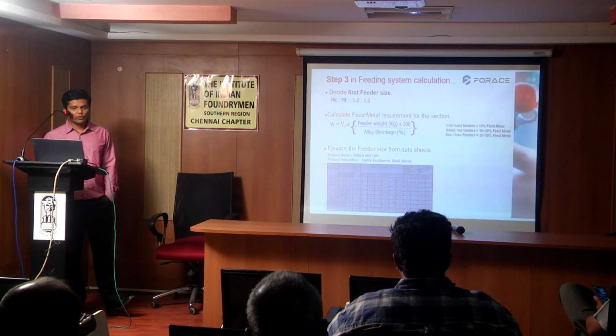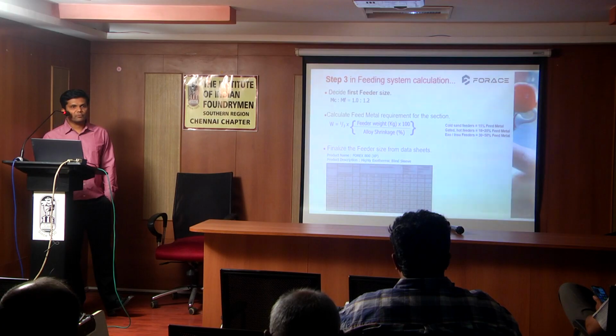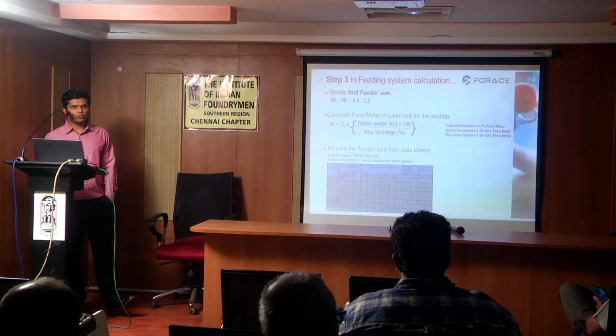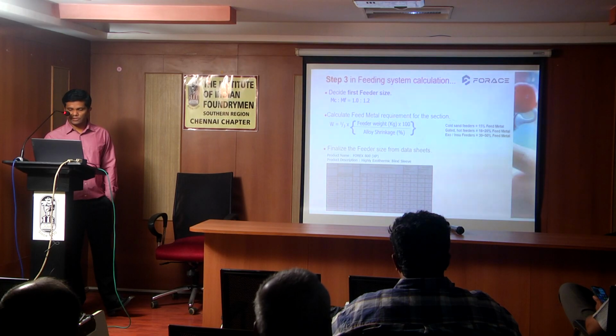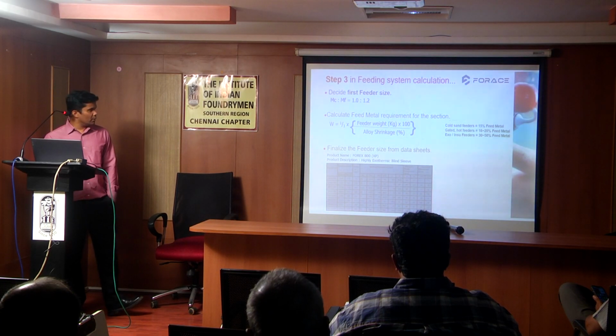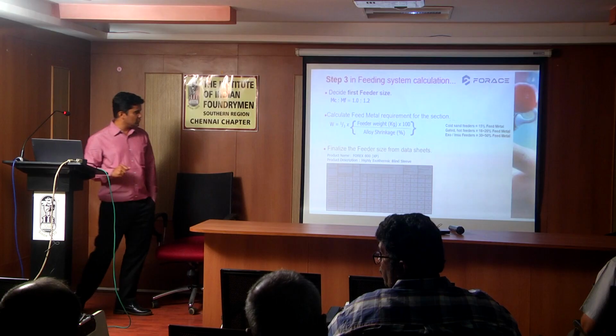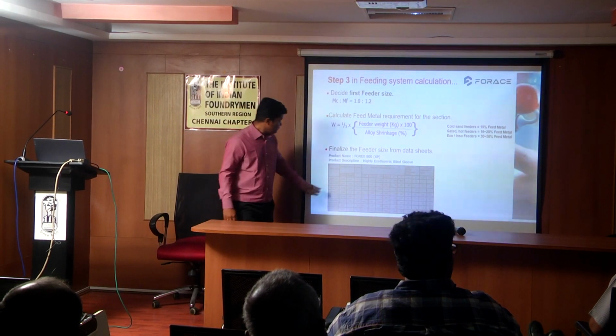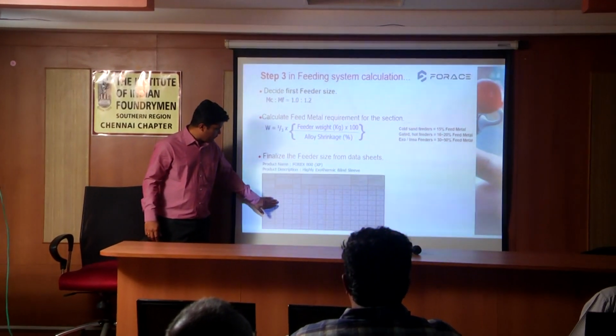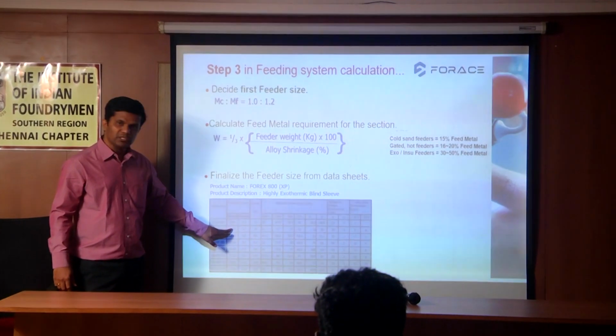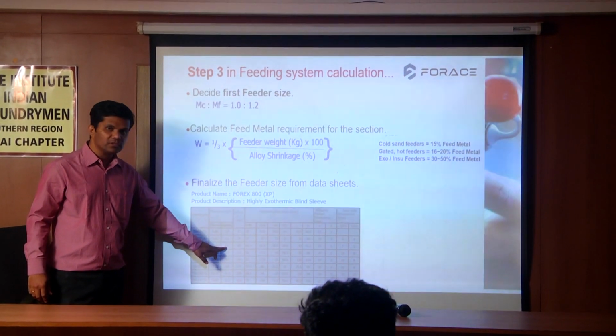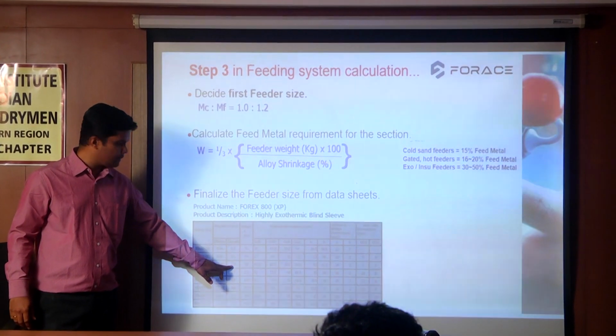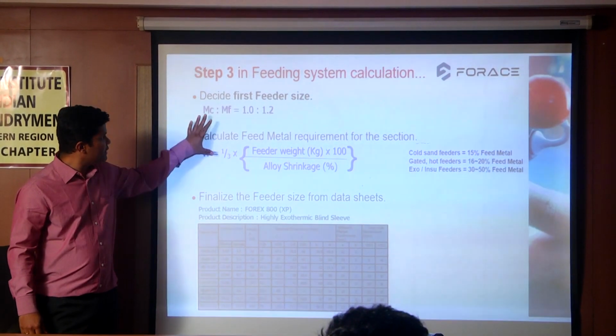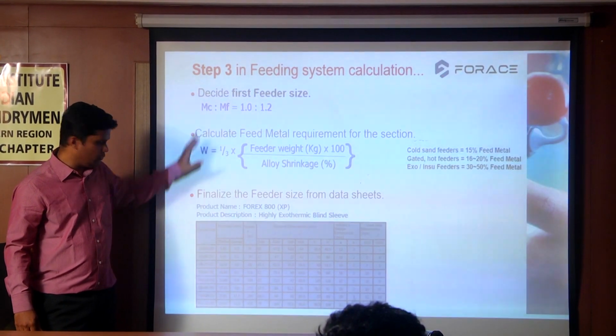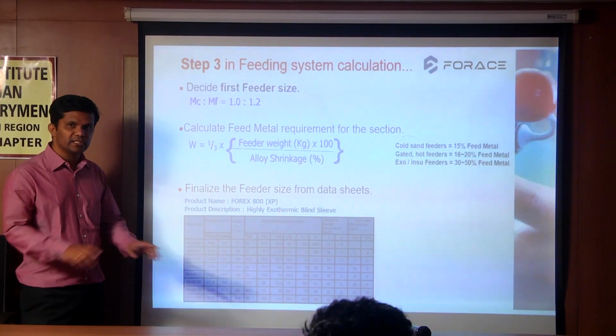Then in the next step, you have to calculate the feed metal requirement of the casting, which will depend upon the alloy which you are going to pour and its shrinkage percentage. So with the available data sheet, this effective modulus denotes the sleeve modulus and this denotes the modulus of the sand riser. With the data sheet and with these two sizes, you can select which riser you have to use.